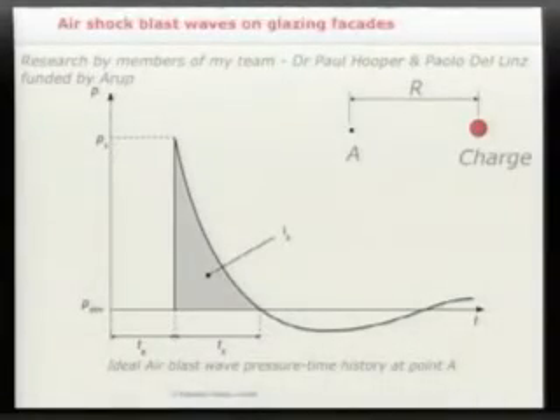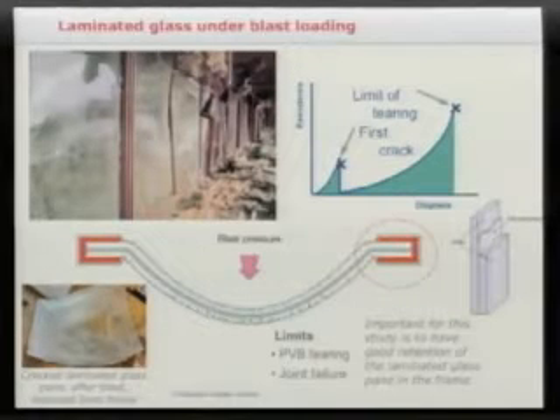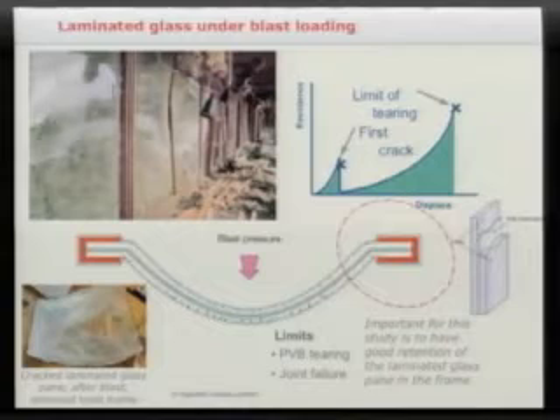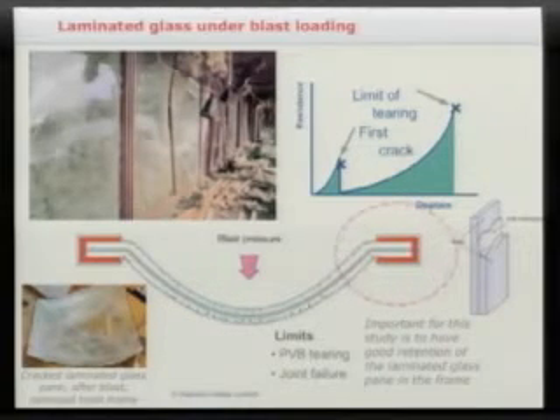The threat is this. This is the typical blast signature. So the pressure rises rapidly to a few atmospheres, then decays over a period of a few milliseconds in the case of an air blast, and sometimes you get a sort of overshoot as well. So there's your typical input into the structure. And the usual way that you design structures to resist this blast is to use laminated glass construction. So you can see here that the blast wave still impinges on the sheet of glass. It fractures the glass, but now the glass remains attached to the PVB interlayer. And the key here in the design of this is to control the limit of tearing of that PVB, but also the pull-out conditions from the joint. And those are the two things that we've focused on in our research.